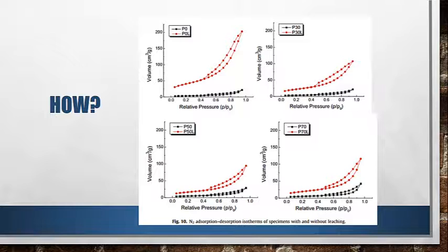For pore structure measurement, the pore structure was measured by water absorption test and N2 adsorption test. The water absorption reflected the porosity of paste through the volume of absorbed water. The relationship of the water absorption and the maximum water absorption will be expressed by the equation, where parameters lambda and alpha represent the index of the apparent diameter of pores and the index of pore homogeneity.